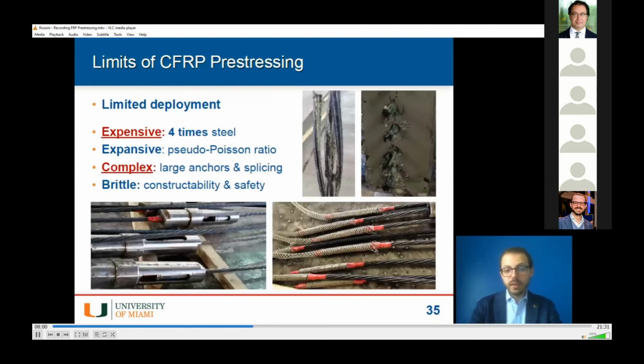First of all, the issues. As I said, carbon pre-stressing is a very effective technology, but it is also a very complex one, for a serious reason. First of all, carbon is an expensive material. It comes at 4 times the cost of traditional steel strands. It has a relatively high pseudo-Poisson ratio that can cause concrete to spall and crack when we release pre-stressing. It's also a complex technology that requires large anchors and splicing, typically proprietary technologies. Finally, it's brittle, and this can be an issue both during constructability, for safety concerns, and also during the service life of the structure, being an unexpected failure mode.